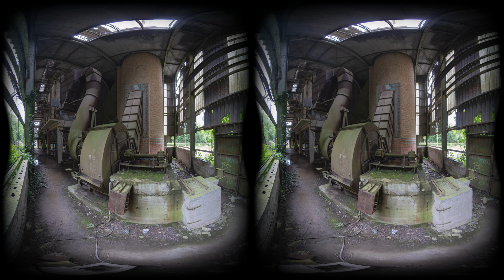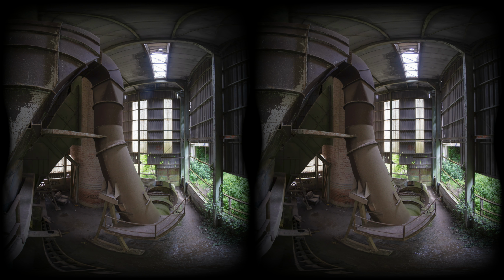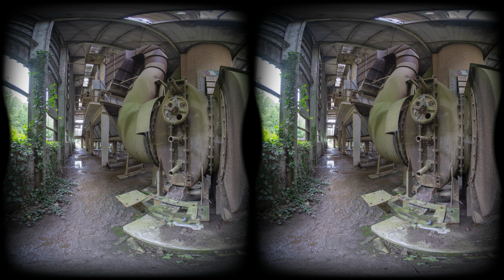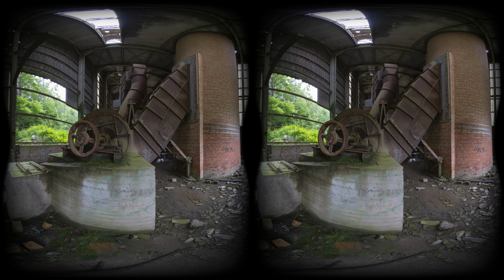The quicklime produced here was used to purify molten pig iron in the blast furnace or converter from undesirable impurities. The highly reactive quicklime primarily binds sulfur and phosphorus, which would otherwise impair the quality of the steel. In addition, it promotes the formation of a thin, free-flowing slag that absorbs impurities and can be easily separated from the metal. Without quicklime, the large-scale production of high-quality steel would be virtually unthinkable.